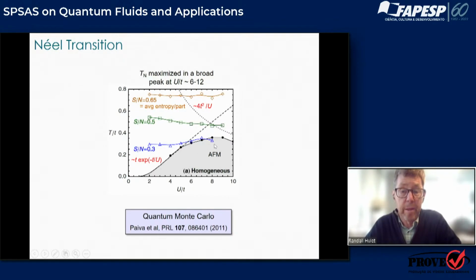And you can see that there's a very gentle maximum where the antiferromagnetic order requires the least amount of cooling. And as long as the entropy per particle drops below about 0.3 kB, you can get into this antiferromagnetic state. If you're at entropy per particle where the spin degree of freedom is random, you're pretty close to this brown line, where the entropy per particle is close to 0.7.